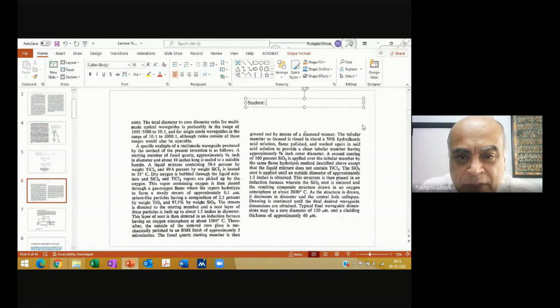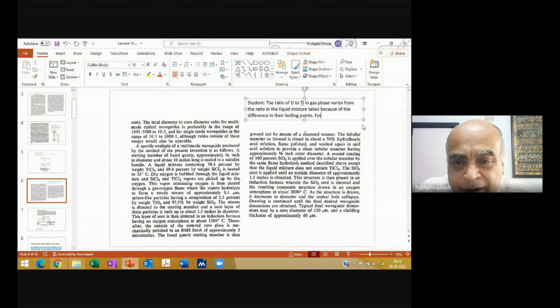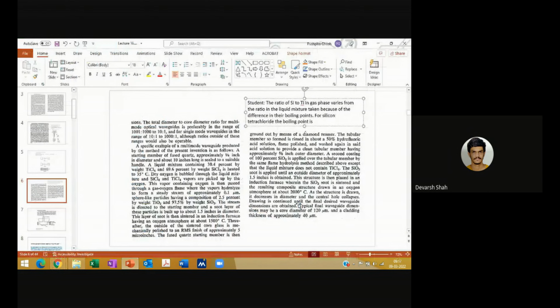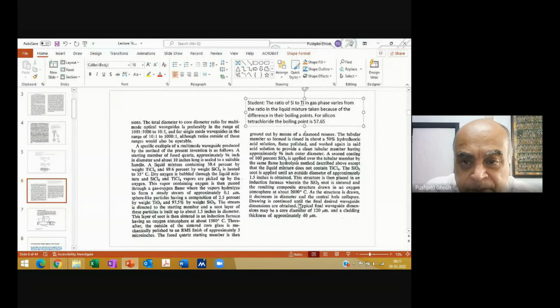The ratio of Si to Ti in gas phase varies from the ratio in the liquid mixture taken because of the difference in their boiling points. For silicon tetrachloride, boiling point is, how much was it? 57.65. 57.65 C. And for titanium tetrachloride, 136.4.